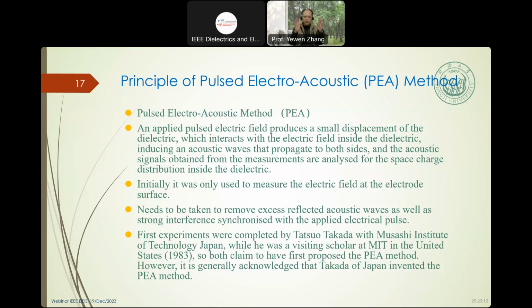So with the electrical field applied voltage, the charge moves a little bit. So it interacts with the electrical field inside of the dielectric, inducing acoustic propagation on both sides. The charge moves a little, in one direction and in the other direction. So the acoustic signal can be obtained from the measurement, as an analyzer for the space charge distribution inside of the dielectrics.